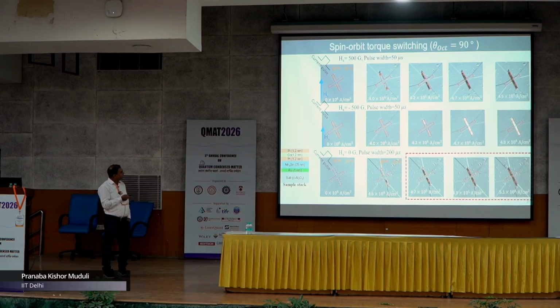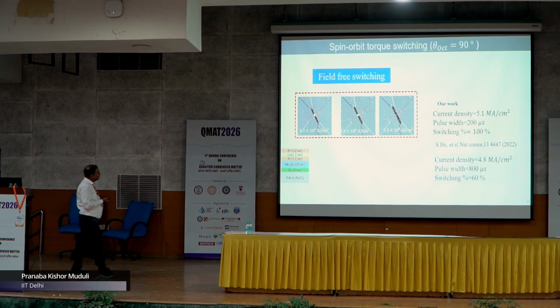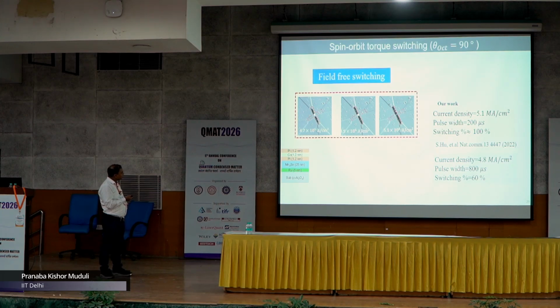And interestingly, switching was already reported in this system, Mn3Ir. If you compare our work with what was reported, you see that in our work the critical current density required for switching is quite comparable to what they had reported, but we are getting this threshold current at a much lower pulse width, whereas here it was 800 microseconds. Also the switching percentage is much higher compared to here. It was only 60%, and we are getting almost 100% switching.